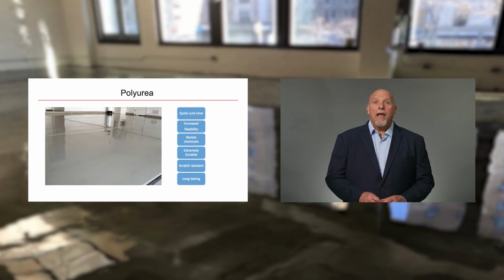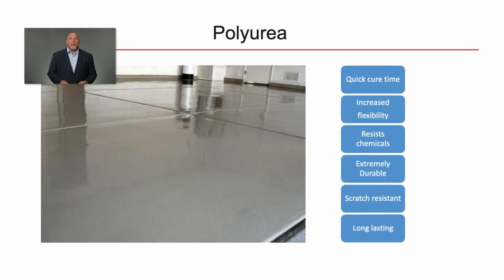Polyurea. A chemist would define polyurea as a type of elastomer derived from the product of reacting an isocyanate component with a synthetic resin blend component. The isocyanate can be aromatic or aliphatic in nature. The result is a rubber or soft plastic compound that may be used in many of the same ways as older protective coating technologies. Polyurea is extremely durable, 20 times more than epoxy. Polyurea is also 98% more flexible than epoxy because polyurea is an elastomer.